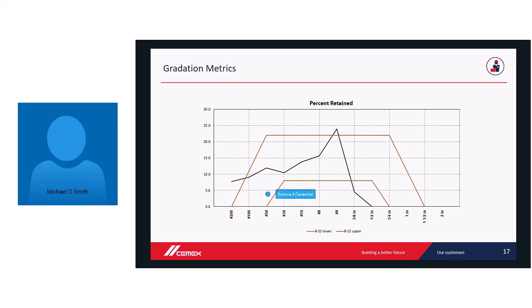Now, if you have more than a couple of screens that drop off or have too much on them, that's a problem. Generally, when you have one screen that peaks or drops, that's probably not going to be too critical. The two screens on either side of it will help carry it. But if you have more than one consecutive sieve size that has either an excess or too little, then you might see issues in your mix of being gap graded or segregation problems, just because there's not enough body to carry all of the concrete or the paste.